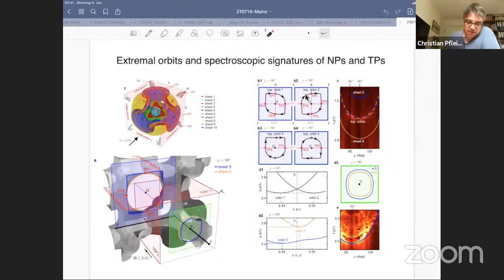On the other hand, in the direction where the nodal plane is suppressed, we would expect, if there would be a nodal plane, that the separation of these orbits, because you see the maximum, the extremal orbits, it would be a little bit before and to the back of the nodal plane, but the symmetry would be the same, right? But what we observe is actually something where we have two different frequencies, right? And again, this is in agreement with calculations. So we see two frequencies here instead of one. And that is an indication that the nodal plane has been suppressed.